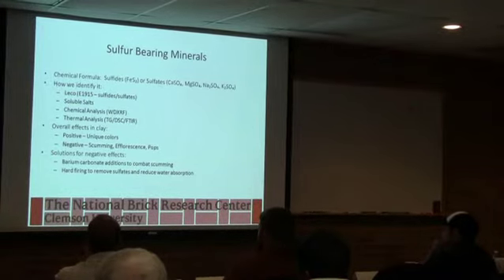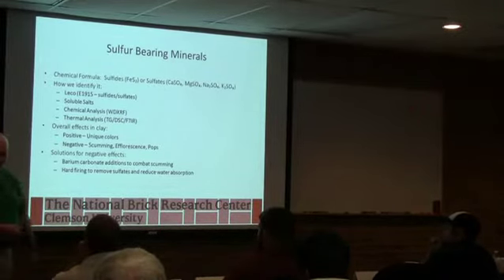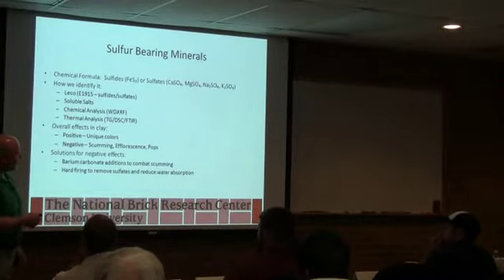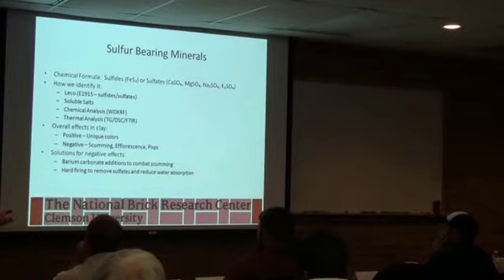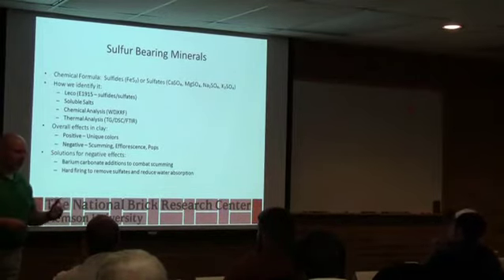I've gotten to the point looking at these things where if you see a heavy white sheen on the brick, it's usually a calcium sulfate. That's the most common. But sometimes you see a crusty deposit on the corners or edges of the brick. Those tend to be sodium or potassium sulfate because they're more soluble and they stay in the water for longer. And you end up seeing those at the edges where the most drying is taking place. So you can tell what you're seeing by the type of salt. There are different ways to look at it, but most of what we do now is a soluble sulfate test, and based on the number, it can give us a good idea of whether there's a potential for either efflorescence or scumming.